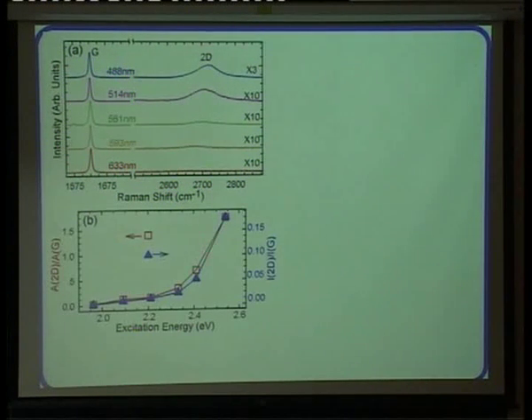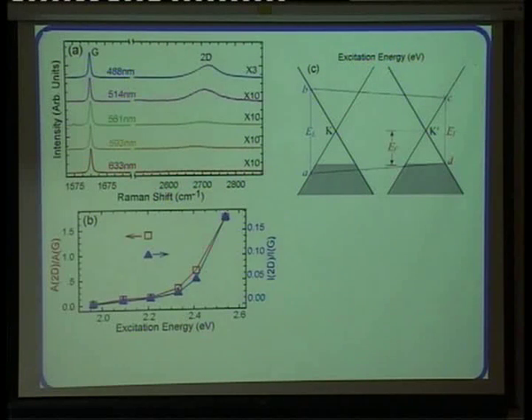But actually, it's not so difficult to understand. It's a very easy situation. It's the simplest situation with respect to the one of the G peak. If I dope enough, because of Pauli blocking, the transition, the most resonant transition that gives rise to the 2D peak, is blocked. And since the non-resonant transitions, as I mentioned before, contribute very little, in fact, this is experimental. Or if we didn't know if they did contribute very little, we can now experimentally prove that they do contribute very little because you don't see anything, okay? So once you kill the most resonant transition by changing the excitation energy, in this case, not by changing the doping, the intensity of the 2D peak can be completely suppressed.